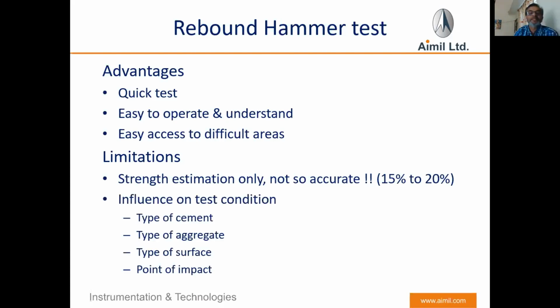Then there is the influence of test conditions, type of cement, type of aggregate. If your concrete has 45 mm, 50 mm aggregate, the surface hardness will be high and the compressive strength will be high. If the aggregate is small in size, you will get quite low compressive strength. Type of surface: if the surface is wet, a less hard surface, you will get a low rebound value and accordingly low compressive strength.